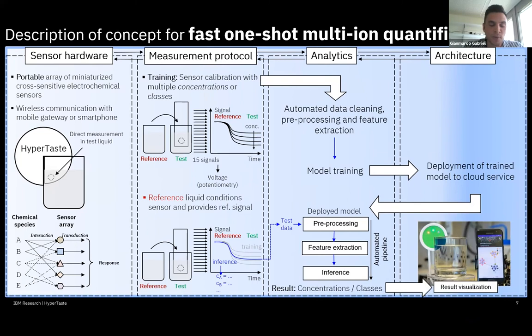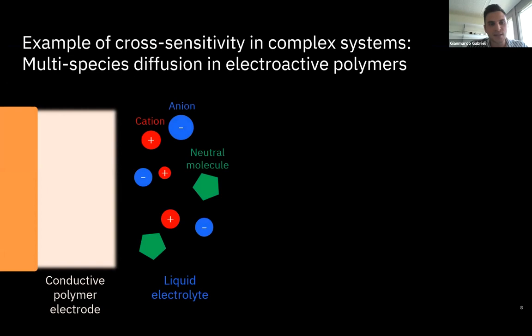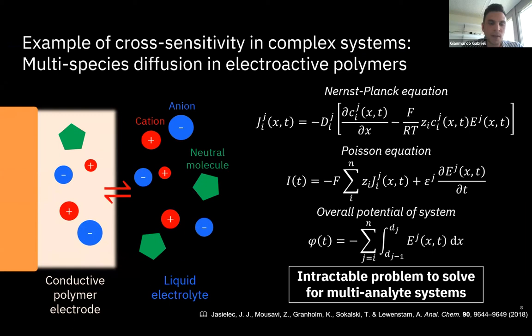So as I said, we use conductive polymers as sensing materials, which are known to interact with both charged molecules and neutral ones. And the overall potential of the system arising at the electrode interface depends on the Nernst-Planck equation and the Poisson equation. However, when we have such a complex system with many targeted ions and the presence of multiple interferents, solving those equations would be quite prohibitive. And that's why, as I said, we shift to a fully chemometric approach with a data-driven multi-sensor array.